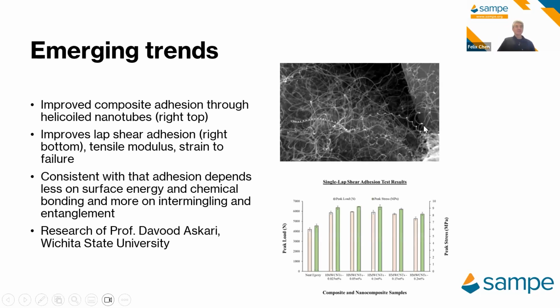On emerging trends, one here is part of a webinar that Professor Davood Askari gave. I think I saw him on this chat, but this is straight from his work, and it deals with using composites and the actual fibers to improve adhesion. The pictures on the right are plucked from his work. The top one shows how he's able to fabricate the fibers to create the coiling that improves the adhesion. The chart at the bottom shows the increase in strength. One thing that struck me is that usually in materials, when you increase the plasticity, you decrease the strength because of the competition between flow and fracture. Here, this is not the case. He's able to get an increase in the toughness and an increase in the strength.